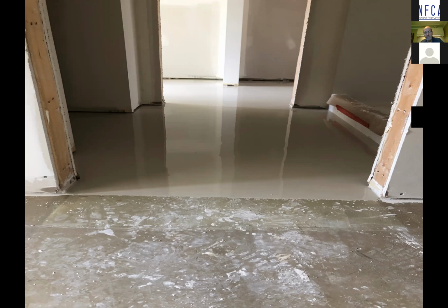But certainly the use of gypsum toppings and gypsum self-leveling underlayments is one way of dealing with floor correction issues on this. And these are not your 80s gypsum materials anymore. So whether it be stuff that our company makes or other manufacturers make, these are all very engineered products that have high compressive strengths, excellent performance ratings, that you can do caster loads, you can do impact on them. They're also not susceptible to softening in the event that there's a spill. One of the concerns is that gypsum materials can emulsify in the presence of moisture. Well, that's not the case with a lot of these new high performance materials. This is not your 80s gyp anymore.